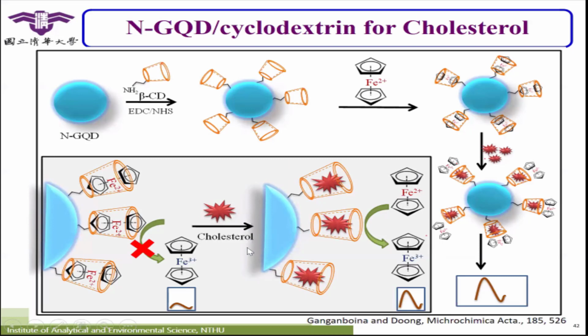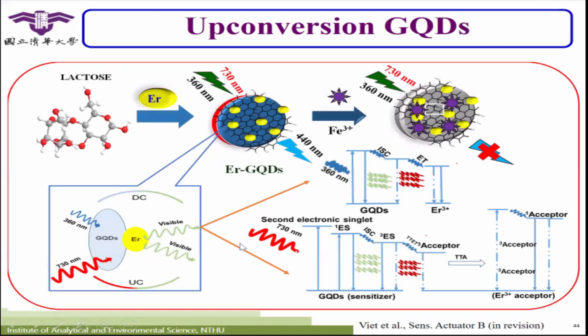You can also use it for upconversion. Upconversion is quite new at this moment. We always know that graphene quantum dots can do down-conversion. For the optical property, we use a low wavelength of 360 nm and they emit at 440 or 460 nanometers. That is the case people would like to use. But one characteristic of GQD is that they have the upconversion property. When you use long wavelengths like 730 nm, they still can emit at around 440 nanometers. What's the advantage?